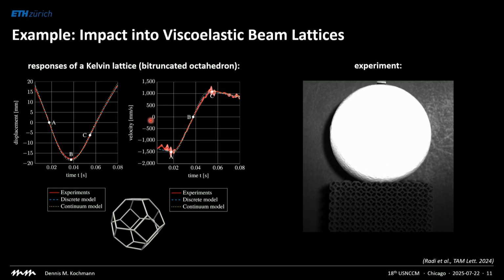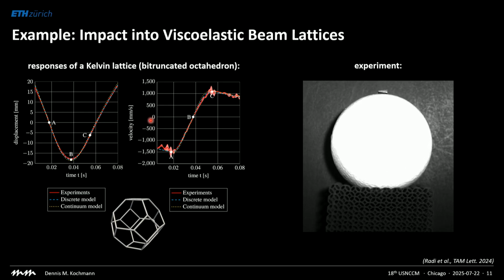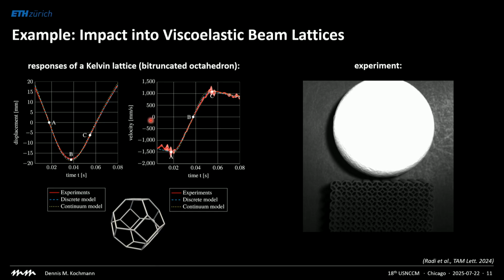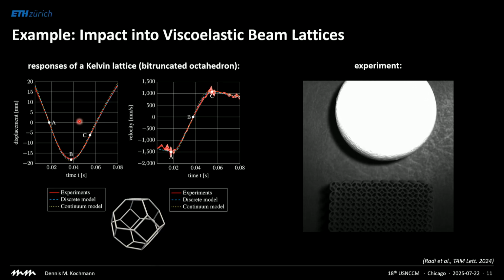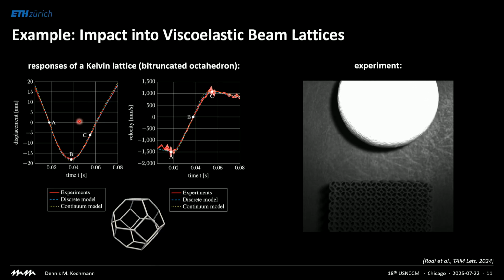If you're designing impact-absorbing mats or shoe soles, you can run the experiment in this case, and you can beautifully compare the experiments to the homogenized FE square simulation and the discrete calculation, and they match very nicely if you know the base material properties. So this is an approach where FE square works very well.